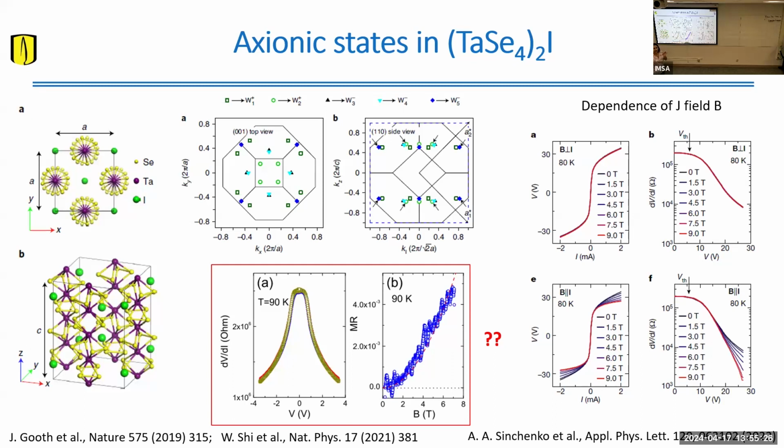So there is a very tricky experimental challenge with IV measurements. For these measurements you need to put in large currents, right? This is an effect that happens above a threshold current. If you put too much current through a material, you can heat it up. You can create some Joule heating, and this heating will actually change your resistance. So if you're not very careful and don't thermally sink your samples very well, you can create artificial effects in your IV curves.